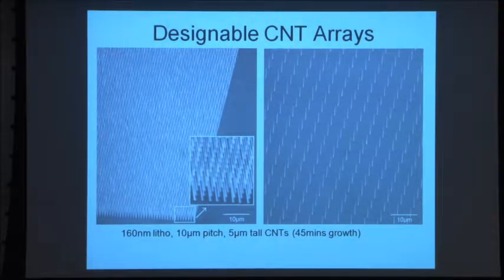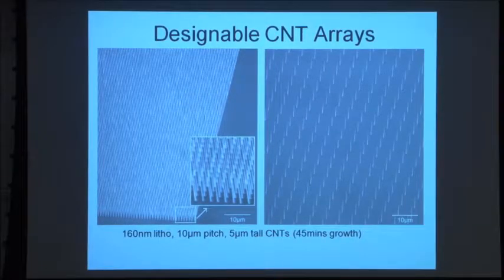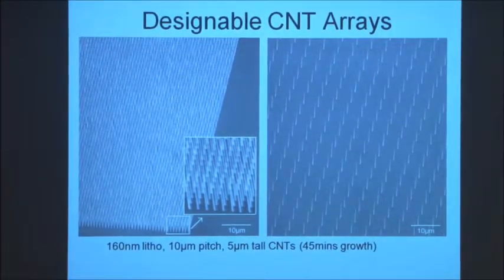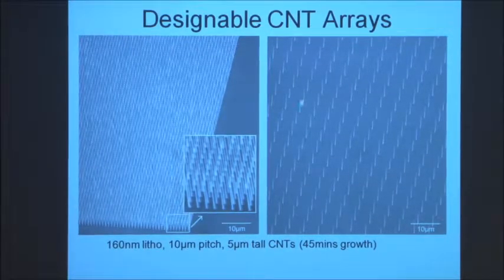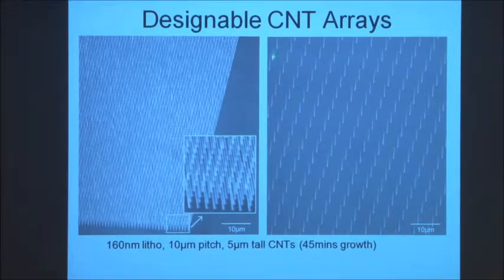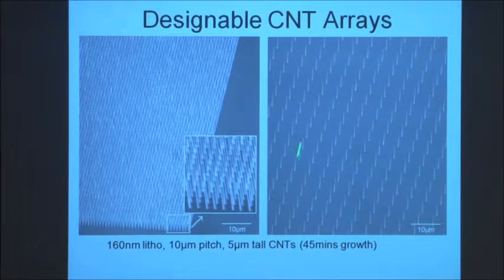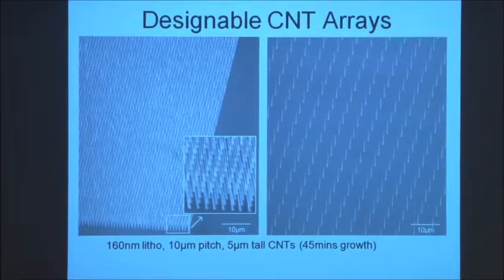For some applications, we also want to be able to accurately control their size if we can. And when you're doing single-wall nanotubes, that's very difficult. But if you grow multi-wall, then it's a bit easier. In this case, what we do is instead of having a thin film of nickel, we actually put down nickel dots, each nickel dot being accurately placed and having the same size by using e-beam lithography or nano-imprint or some other technique like that. Then you grow the nanotubes from exactly the same size of nickel, and the size of the nickel dot tells you what the diameter of the nanotube is going to be, and the temperature and the time gives you the height. So we can now control at least the height, the diameter, and the position by accurate control and placement of these nickel dots. But that's for multi-wall tubes.